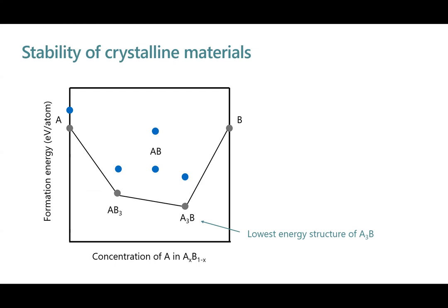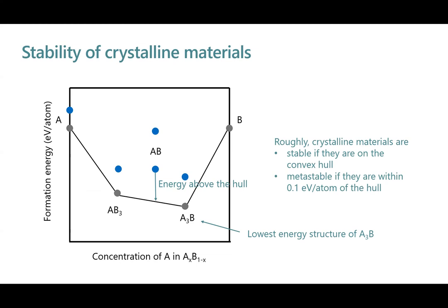Now let me introduce an important concept called energy above the hull, which is basically the distance of your energy with respect to this hull. A material is stable if it's on the convex hull, but materials can also be metastable, meaning they are not purely stable but can still be synthesized. Diamond is one example that is metastable. But usually people consider it stable if it's within 0.1 eV per atom. All this energy you can compute with quantum mechanics, and that is how we define whether materials are stable in our problem. Then you can evaluate any crystal you generate here.